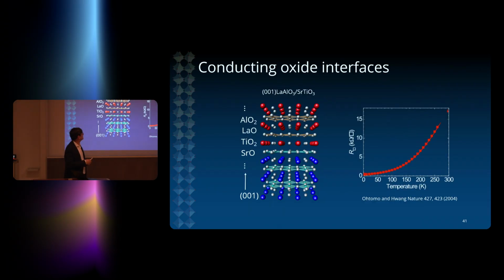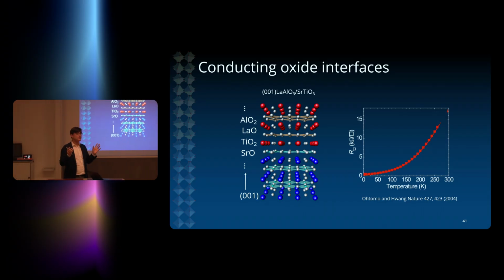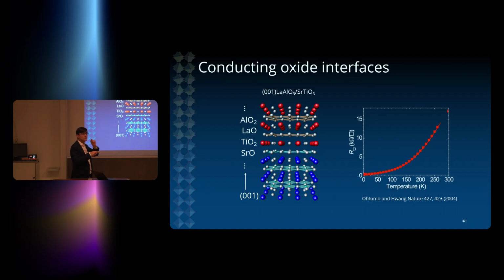Some of these materials are insulating, but as I told you before, these Lego blocks are dynamic. When you take some of these insulators and bring them next to each other, they completely change their properties. This is an example of two insulating materials, strontium titanate and lanthanum aluminate. These are good insulators in the bulk: a 3.2 electron volt band gap and a 5.6 electron volt band gap. You bring them next to each other, and automatically at the interface you get a two-dimensional electron system of metallic electrons.